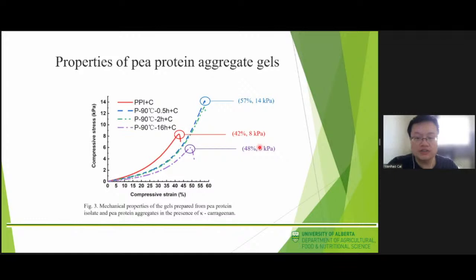As for carrageenan, the formed gels were too soft to be self-standing due to the low κ-carrageenan concentration of 0.5% applied in this work. Previous work also reported the formation of very weak gels by κ-carrageenan, like 1%, without the addition of cations. However, the addition of some κ-carrageenan, like 0.5%, to untreated pea protein solution or pea protein aggregate suspension led to the formation of gels with good mechanical property. In this figure, it displays the compressive strain curve of the complex pea protein carrageenan gels.